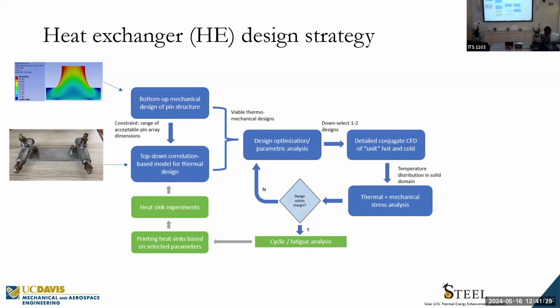What we're trying to do here is to select a correlation that will best match our experimental results. What you see over there is a heat sink, and inside of the heat sink, you basically have the pins that we expect to have in the final heat exchanger. We run experiments on these, and based on the Nusselt number and friction factor that we're observing, we compare these results to the experiment to select a correlation in the literature that will best represent the thermal behavior of our unit.